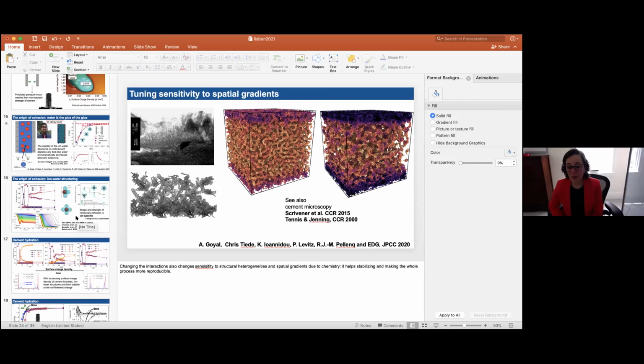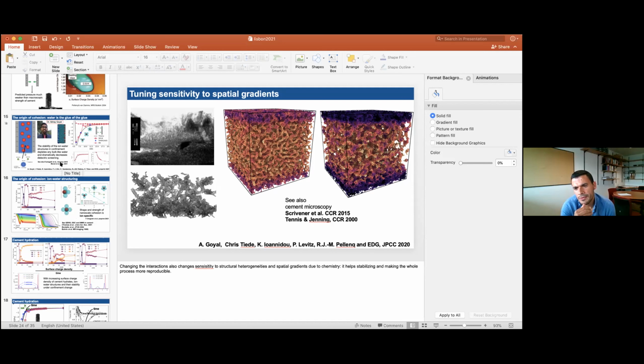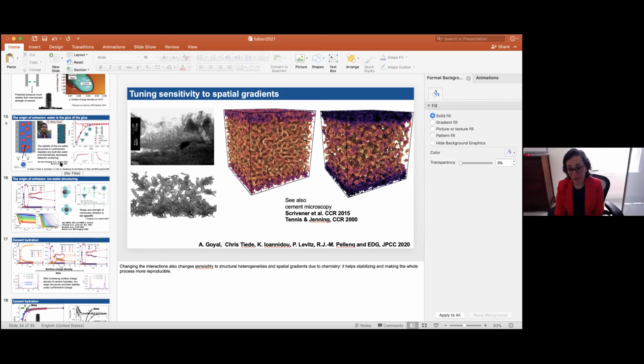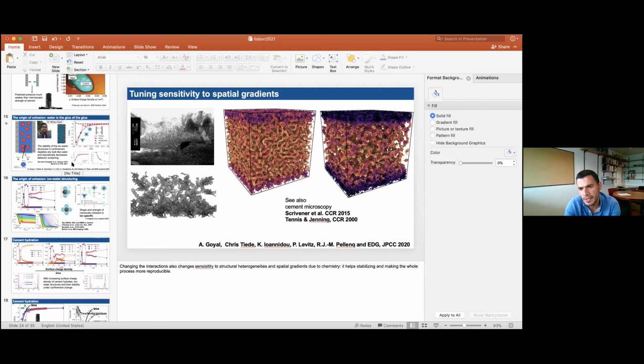Basically you have to imagine that you have the grains, and then the grains progressively dissolve, and this material is precipitating continuously. So the number of nanoparticles, the volume fraction of the nanoparticles, is increasing over time. And so what we mimic with the change of confinement, basically the densification, should correspond to the densification process of the system. So you have a larger amount of nanoparticles produced over time, and this makes the distance between nanoparticles shorter and shorter. But the surface charge is always the same, or is it also evolving? At the same time, the surface charge is evolving. Okay. Otherwise, the energy cost of putting another particle there will increase.